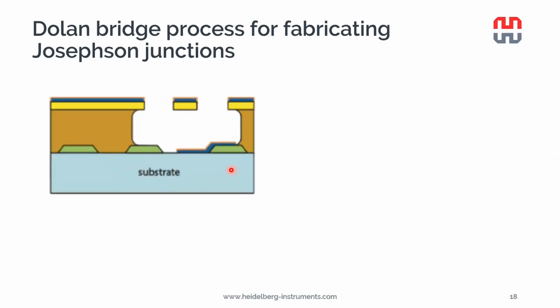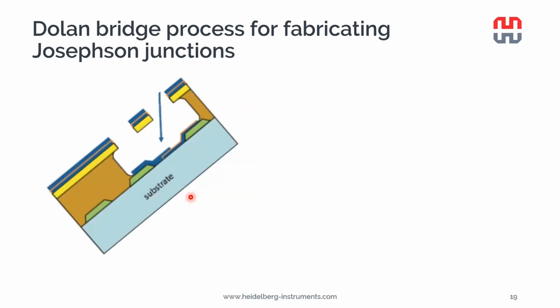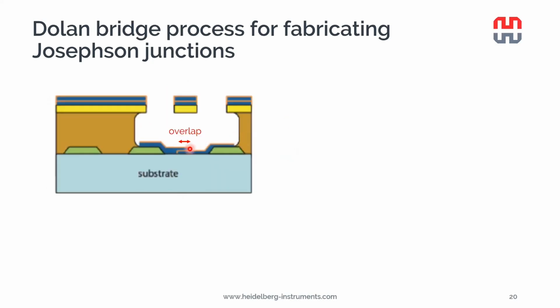If the metal we evaporated is aluminium, for example, we just vent the evaporator, and a very thin and very high quality oxide is formed over the aluminium electrode. We can continue the process by tilting the sample to another direction, and in this case then we can make a connection with the already evaporated metal electrode underneath the suspended bridge. The nice thing here is that the overlap can be very definedly tuned by adjusting the tilting angle. So we can fabricate using the same geometry different kinds of Josephson junctions with different overlaps.